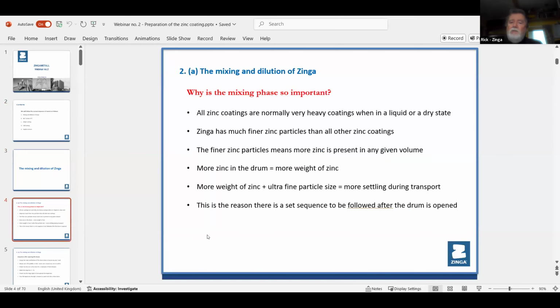All zinc coatings are very heavy in the liquid state. So when you pick up the drum, you feel it's very, very heavy. The zinc particles in Zinga are much smaller than the zinc particles you find in paint. This is why in very, very small gaps, the Zinga will go right inside. It can gain access, and that's why when you're coating over rust, it goes inside the rust, because the particles are so small. But because there are more particles in, for example, a 1 gallon tin, 5 liters, it's 2.7 times the weight of paint. That's how much zinc is inside there, and that's why we have such a good voltage of electrons flowing from the zinc.